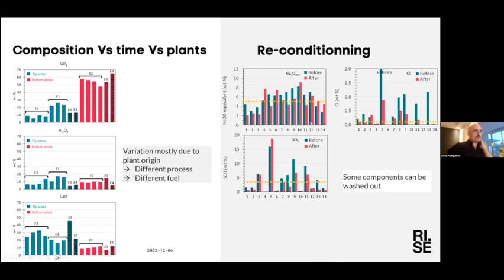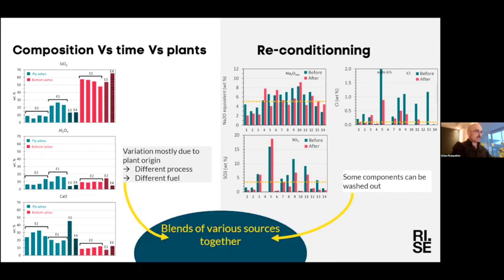So in some cases, we could reach acceptable limits. So this white line is the limits that we have in the standard, so we cannot go higher. In some cases, we are still quite a way above those. But it still seems that in most cases, we can get rid of them and be at a good level.